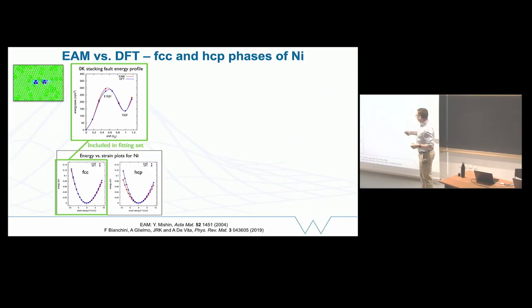We also put in information about the stacking fault, so the energy of taking half a crystal and sliding it on top of another one. And so we get that right as well. You can see the red and the blue. You may not be able to read the caption, but when red and blue line up well, that's good. The embedded atom model is matching the DFT. So these things were optimized for when building the model.